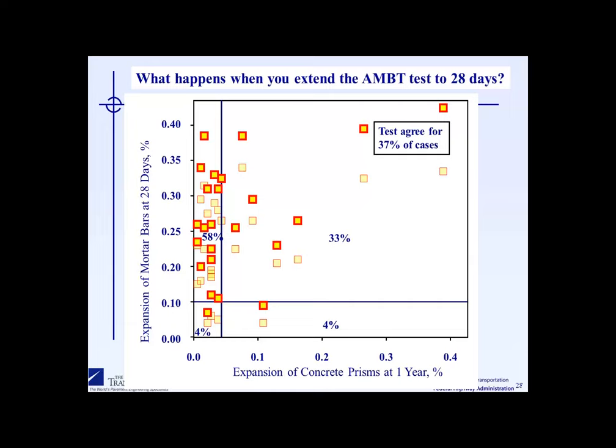Now, as I've said, there has been a suggestion to increase this test duration to 28 days, and as one would expect, as we increase the test duration to 28 days, even more aggregates will fail that have actually passed the concrete prism tests and that are known to be non-reactive. So now we're only getting agreement about a third of the time.